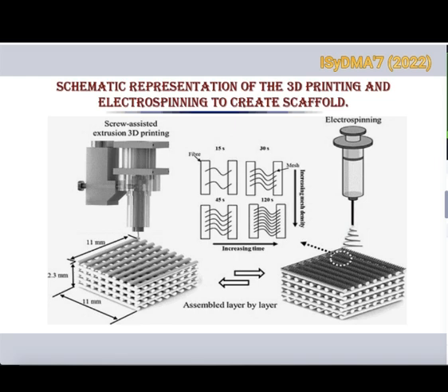So the production of nanofibers directly on a 3D printed microfiber collector, as you could see, we can continue to scan from one to the other and then make these types of structures. The software was pre-programmed to pause at a specific layer to allow electrospinning before further printing can be resumed. So this is obviously a method which has a tremendous amount of applications.